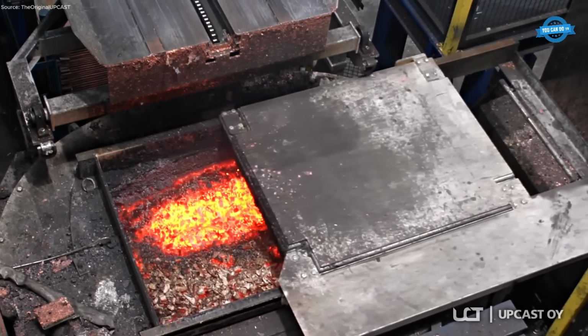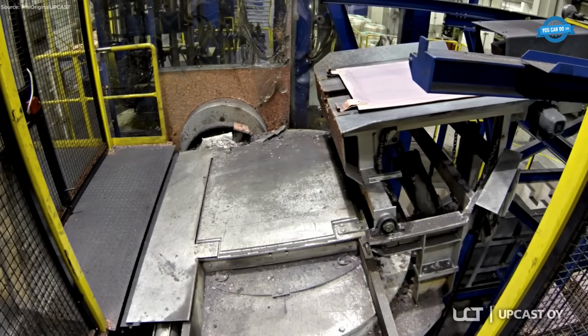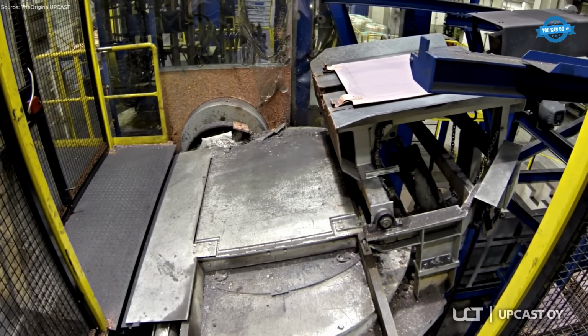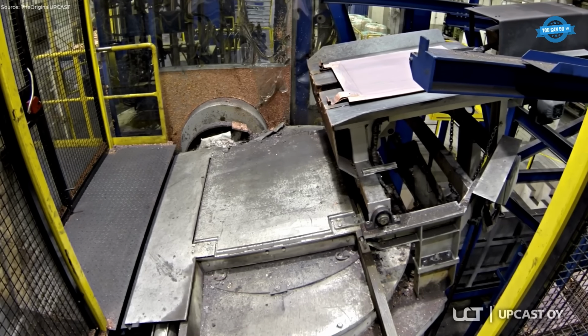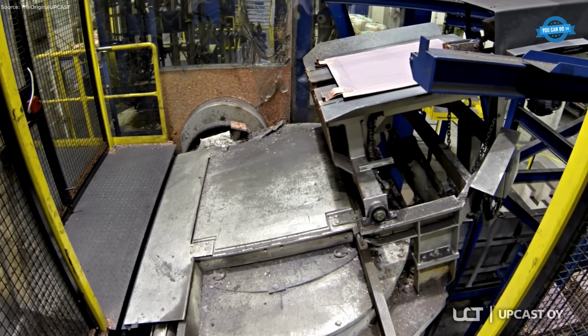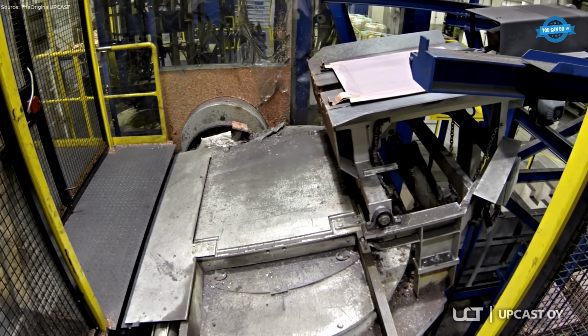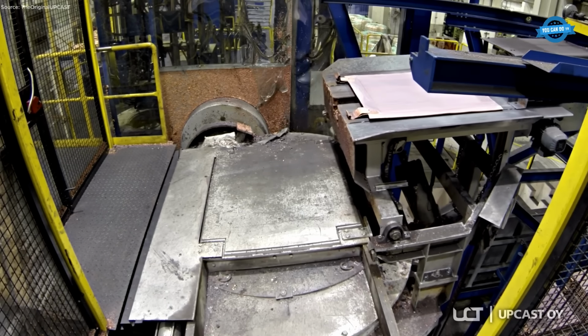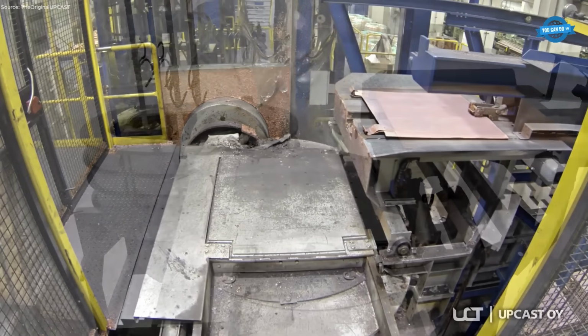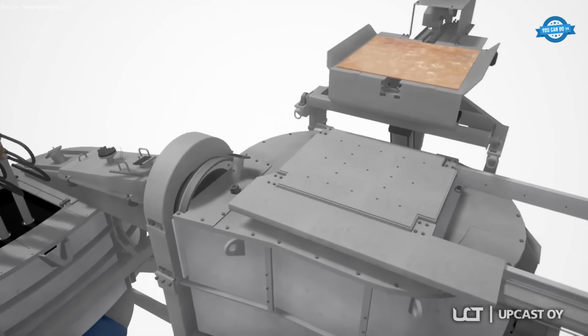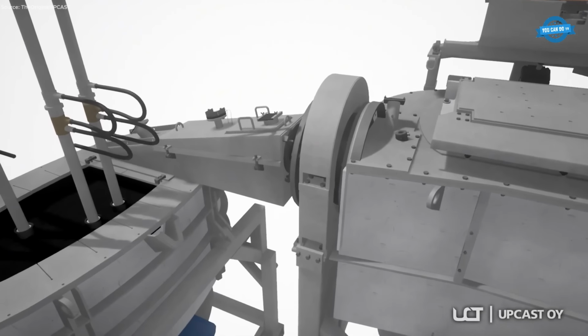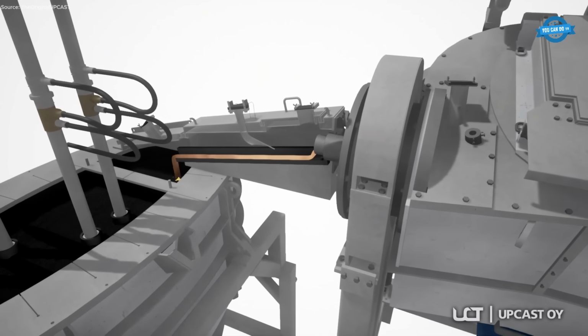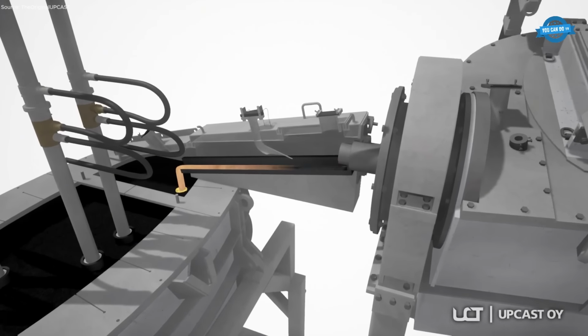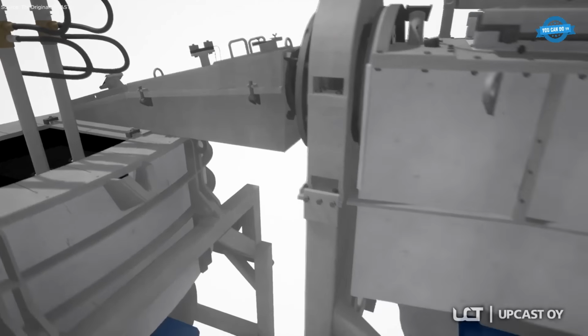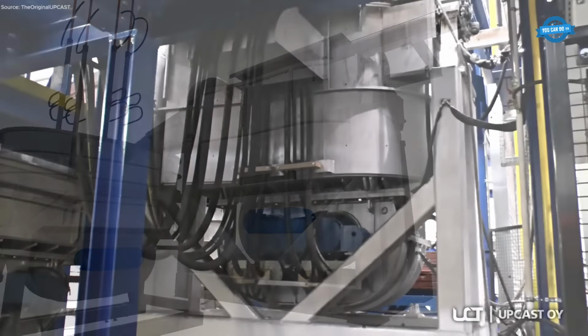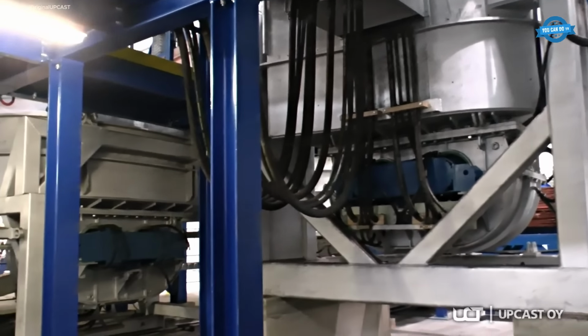Furnace configurations vary according to production scale. The single furnace design, compact and open top, integrates melting and casting in one unit, ideal for capacities up to 12,000 tons per year. For higher outputs, the double furnace setup separates melting and casting, handling up to 40,000 tons annually. When both cathodes and recycled copper are used, a triple furnace configuration, 2 melting units feeding a dedicated casting furnace, offers the best performance.